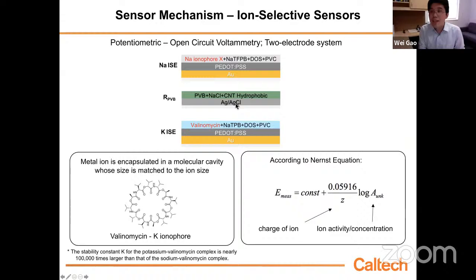That means the voltage will be influenced by the chloride. That's why, to minimize the influence from chloride, we coat this silver-silver chloride with a polymeric film, which is a hydrophobic film that contains saturated sodium chloride as a buffer film. In this case, no matter how external ion level changes, the reference voltage remains very stable. In this case, we can get accurate measurement for different types of electrolytes.